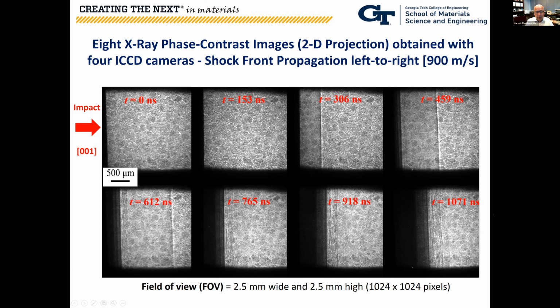You can see this contrast. At 0 and 153 nanoseconds, and at 306 nanoseconds, you see the sharp line, the arrival of that shock front, and the contrast there is clear. It's very obvious. At a later time, 459 nanoseconds, the shock front has propagated further. At 612 nanoseconds, again, it is propagated even further.